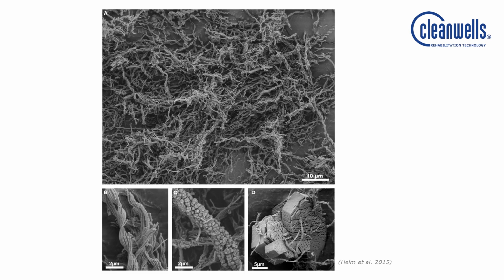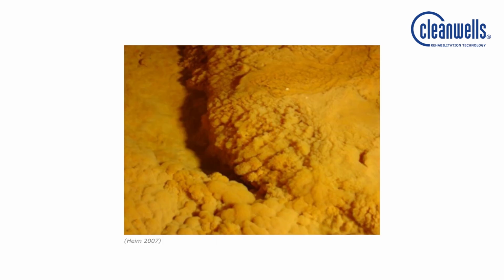Picture A on top shows 2 months old twisted stalks of Gallionella and Mariprofundus. At this stage, they still have a pristine filamentous structure, which we see in the detailed picture B. However, after 9 months, the same stalks in picture C show already a heavy iron oxyhydroxide impregnation. Over time, these soft metastable phases with high surface energy of this voluminous mass of iron 3 age into more stable phases with lower surface energy, finally turning into goethite.